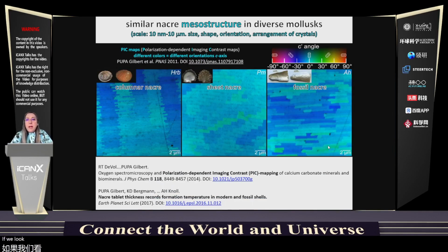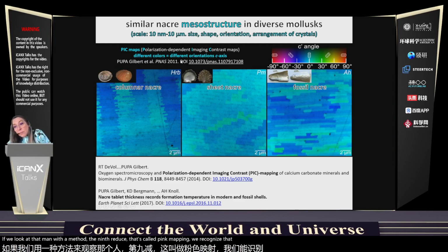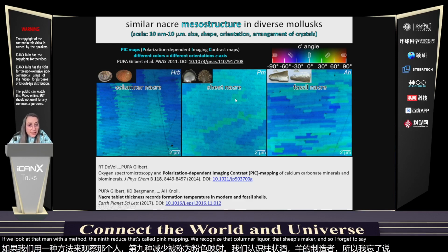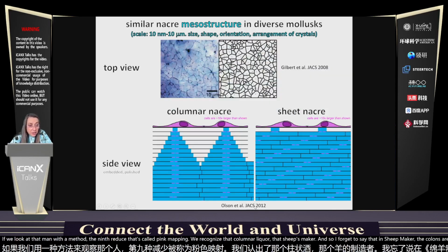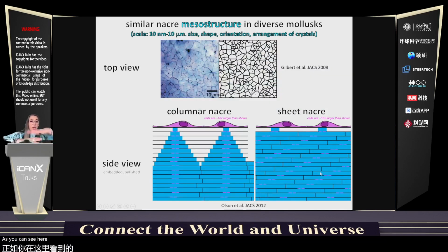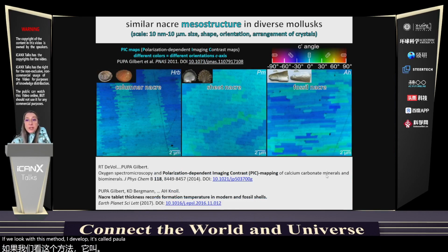If we look at them with a method that I introduced called PIC mapping, we recognize columnar nacre, that sheet nacre. And I forgot to say that in sheet nacre, the columns are actually staggered diagonally, as you can see here. So the co-oriented tablets are staggered diagonally. If we look with this method I developed, called polarization dependent imaging contrast mapping, you can see in different colors different orientations of the crystalline c-axis.